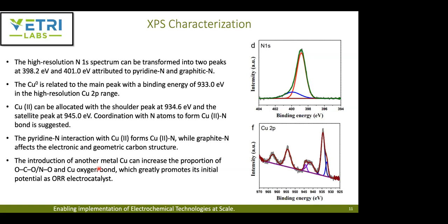But they didn't see all four of these nitrogen peaks. Rather, they noticed only two: the pyridinic nitrogen, at about 398.2 eV, and the graphitic nitrogen, at about 401 eV. And as you can see, the majority of the nitrogen present in the structure is dominated by pyridinic nitrogen. And with this copper 2p, they can see the major peak at about 933 eV is related to zero-valent copper. And they also have the presence of copper 2+, around 934.6 eV, and the satellite peak is about 945 eV. So this confirms the coordination with the nitrogen atoms to form the Cu2+-N.